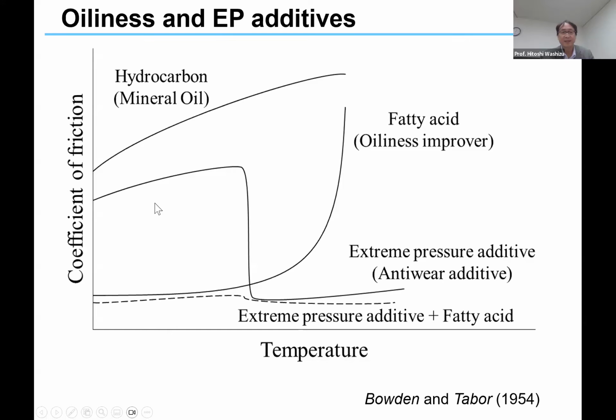improver is like a fatty acid, which I previously showed, and this works here, and these kinds of additives work at low temperature. Okay, and there is another kind of additive named EP additives. This is anti-wear additives, but these additives do not work at low temperature. Why is this? These have phosphate and this has carbonate. Carbonate works at low temperature, and phosphate works at high temperature.